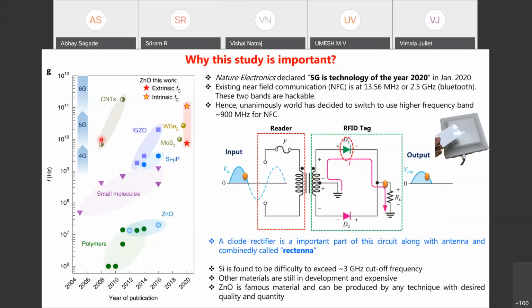Some of the competitors are carbon nanotubes. Back in 2008 and 2010, these were shown to be very promising materials, showing cutoff frequencies in the range of 10^11 hertz. But controlling these devices and getting high reproducibility from them has been challenging. That's why zinc oxide based materials like indium gallium zinc oxide, or IGZO in short, have come up with new improved performance, and this is being preferred right now in the industry. It shows a good cutoff frequency up to 10 gigahertz.